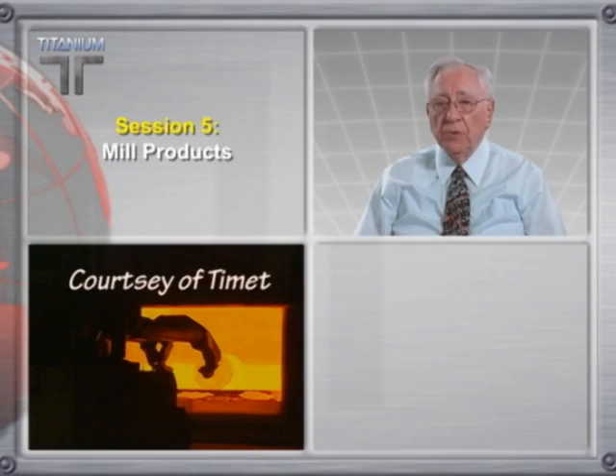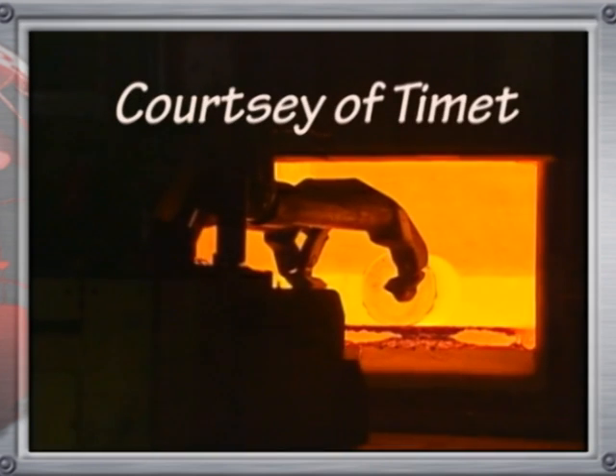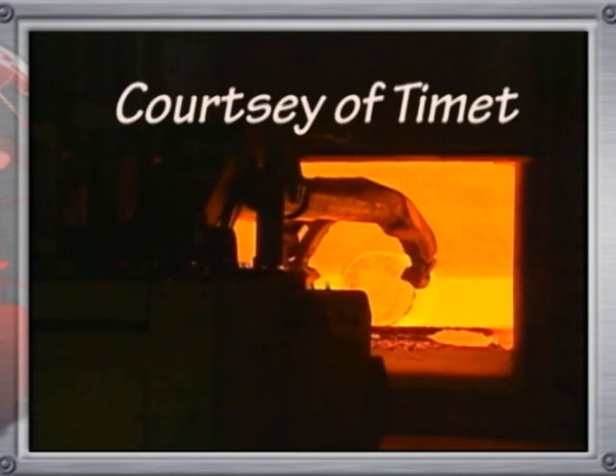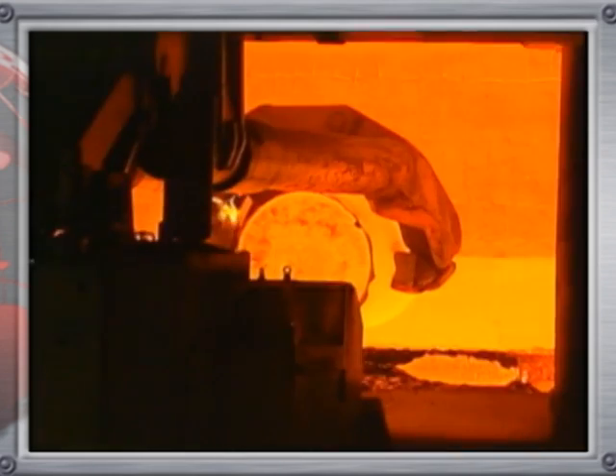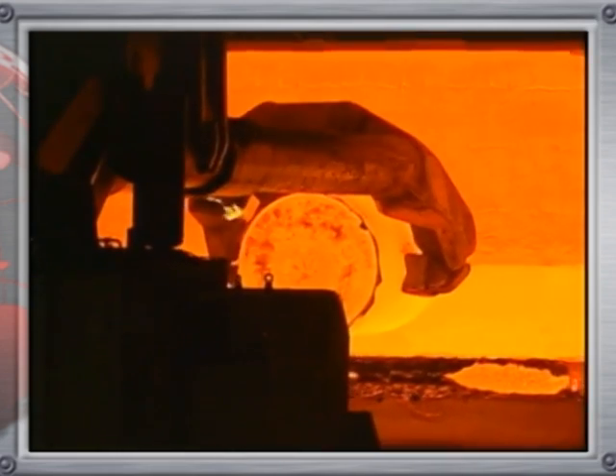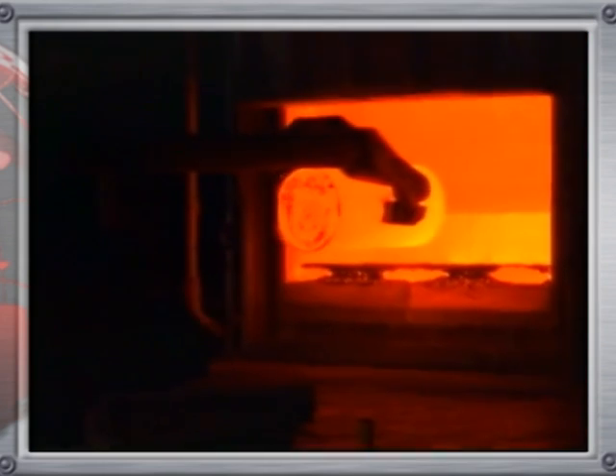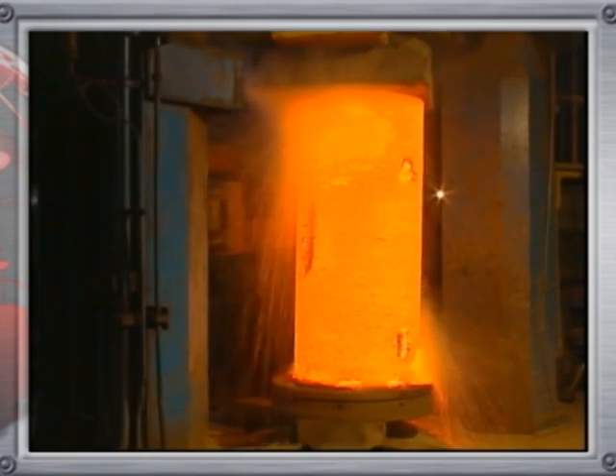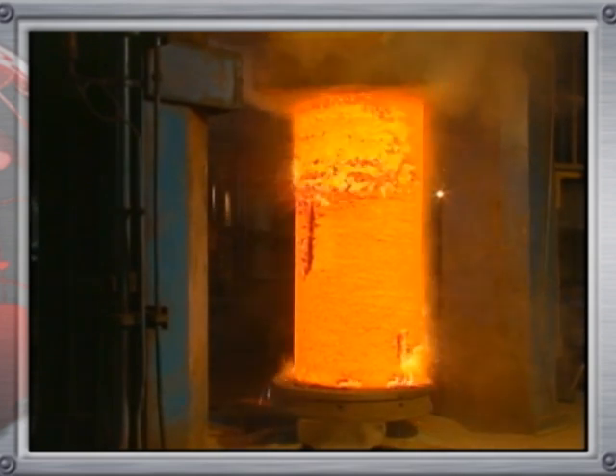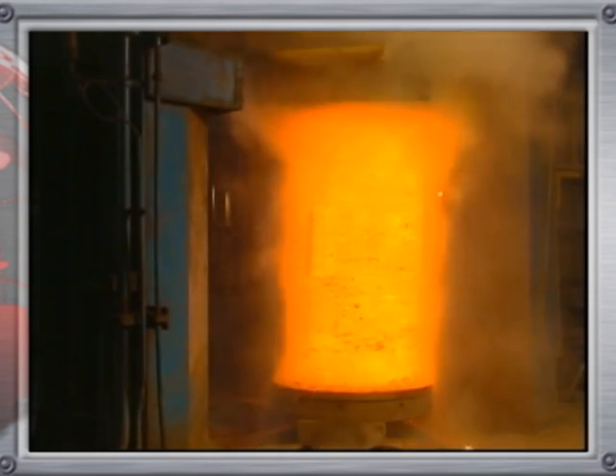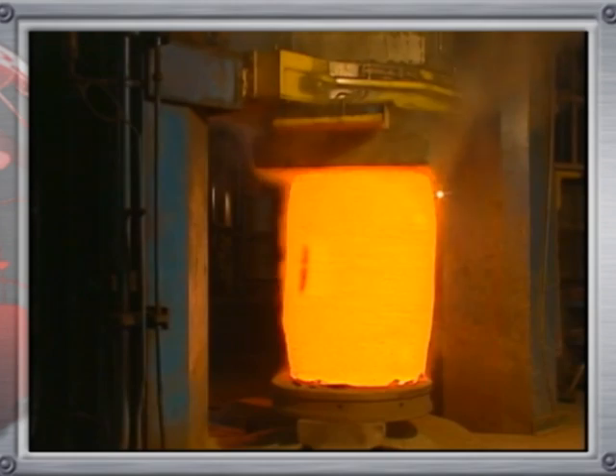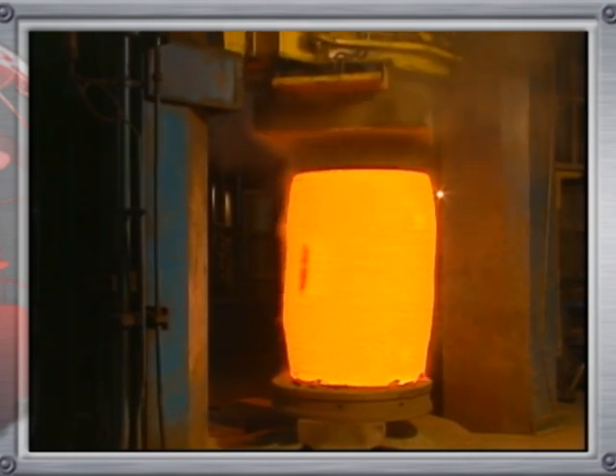This video shows an ingot being forged at TIMET. Here we see a manipulator pulling an ingot out of the furnace. Temperature here probably is above 2000 Fahrenheit. This manipulator will take it over to the forge press, and it's what we call upsetting the ingot. And you can see the titanium oxide coming off the ingot as it was upset.